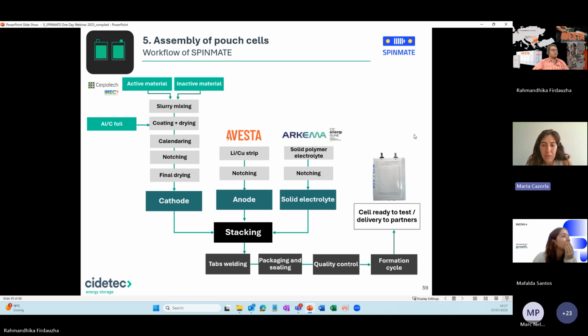So here it's a bit of a summary on how this is done in SPINMATE. As I've explained, what we do in CIDETEC: we take active and inactive materials, we do the mixing, coating, calendering, notching, and final drying. These active materials come from Cerpotech that, as you've already watched, was developed with the help of IREC. And once we have our cathodes and our anodes that are done by Avesta, we notch them, so we cut them into a certain shape, depending on the capacity of the cells we're assembling. And we also have the solid electrolytes, which are upscaled by Arkema with the support of CIC energiGUNE.